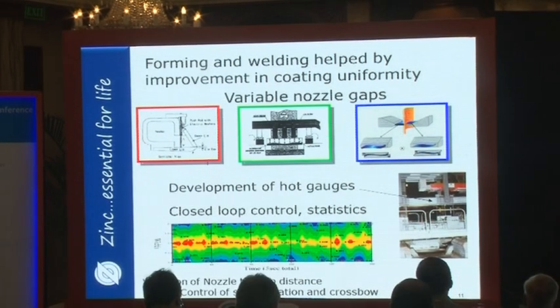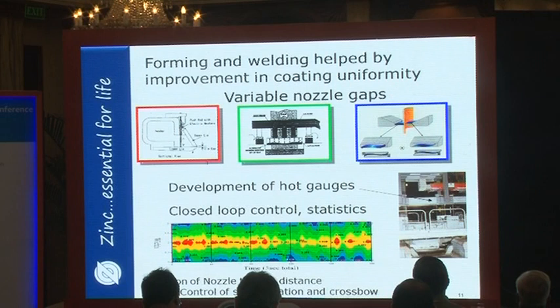So to reduce the variability of forming performance, we really needed to use coating weight controls that are now based on feed-forward models, and we use hot gauges. We show here just a picture of a hot gauge directly above the pot. You can see it just here. Then this allows for a direct feedback.